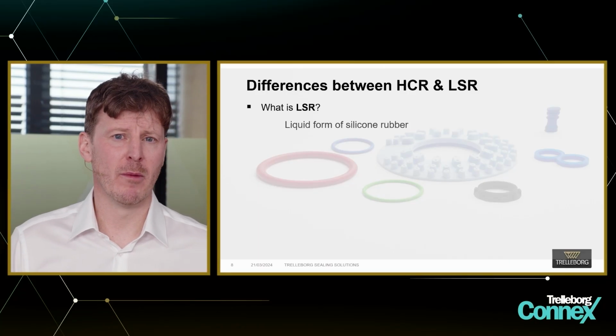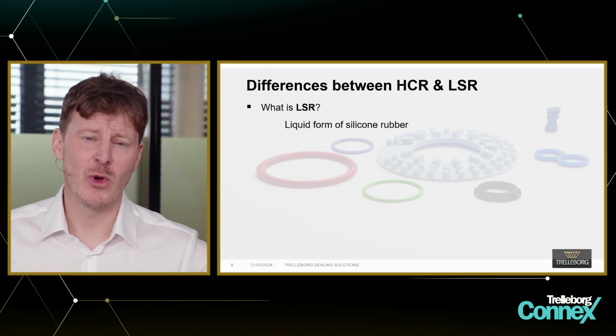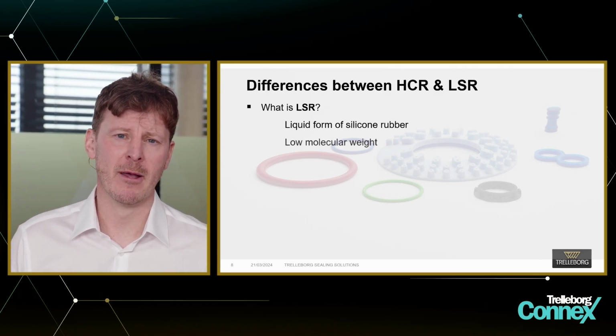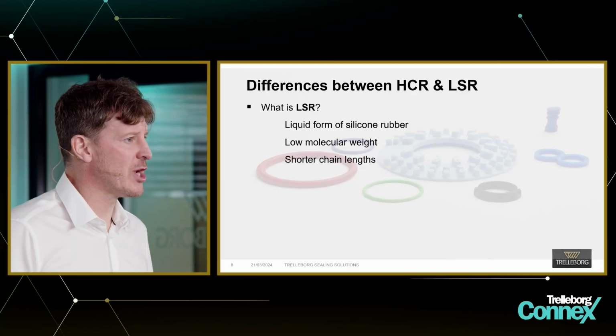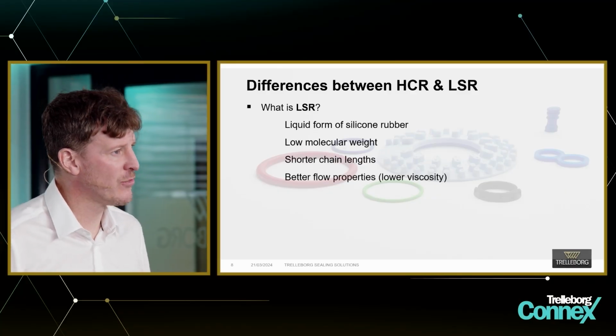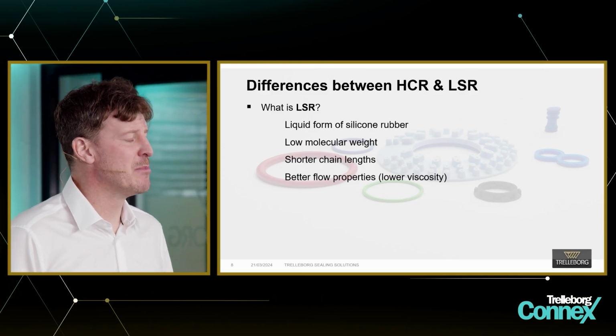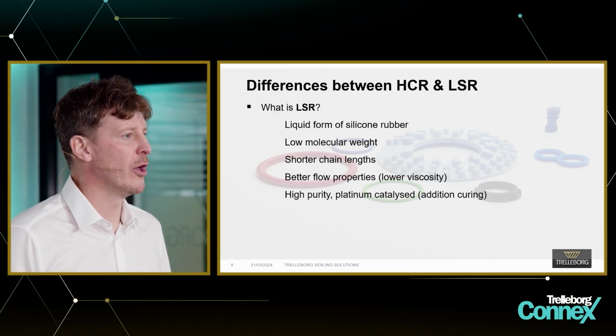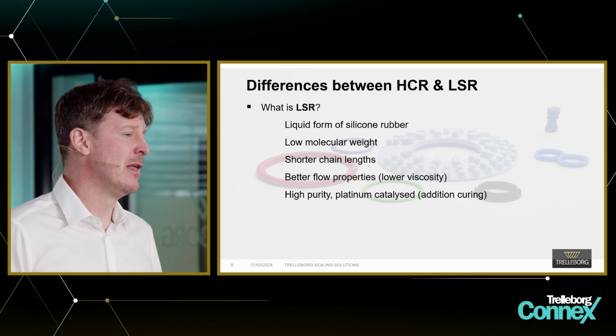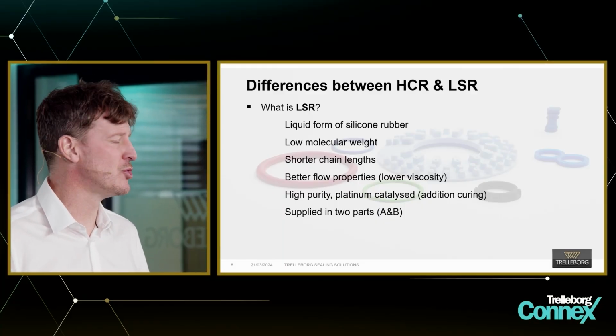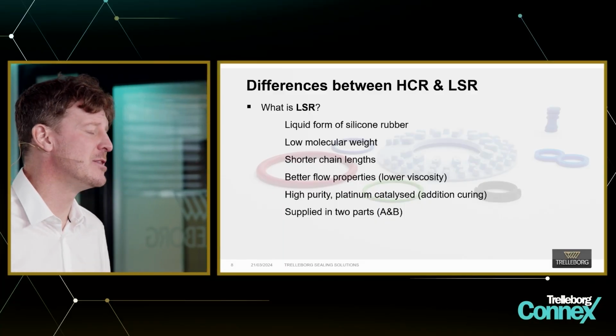What is liquid silicone rubber? Well, as the name suggests, it is a liquid or liquid-like form of silicone rubber. It has a lower molecular weight. Chemically, they're very much the same. They actually have the same chemical backbone, but the way in which it's polymerized gives rise to this very low molecular weight with LSR. Much shorter chain lengths, which in turn allows for better flow properties, lower viscosity, enabling intricate mold flow. It is obviously a high purity material, and as I mentioned before, platinum catalyzed. It typically is also supplied in two parts, A and B. Now, these tend to be a 50-50 mixing ratio, but not always the case. But generally, LSR is supplied in two parts.